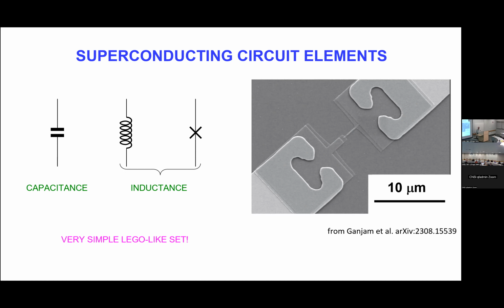I'm just confused because on both sides you have two layers. You don't need it, right? You could have had one on one side and one on the other. Yes, exactly. That's a very good question. You could indeed deposit a first layer and then a second layer, but the problem is that when you do a second lithography step, you're going to damage considerably this very thin oxide layer that you have grown. So the only way to make a junction is that this first oxide layer has to be completely pristine when you deposit the second layer.